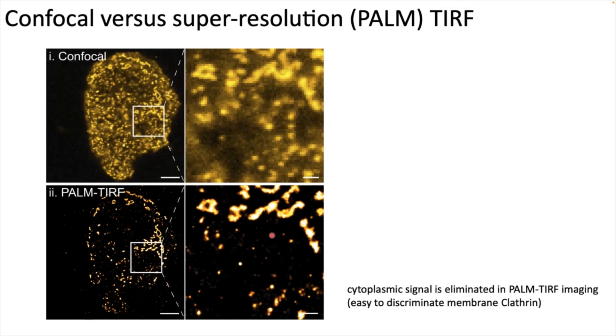It's just related to the fact that we are measuring in TIRF. And as a consequence, we only really image the clathrin that is on the plasma membrane. And on confocal, even though you have some Z sectioning, you still have around 600 nanometers that you image. And as a consequence, you get some of the clathrin that is just above the membrane being endocytosed. So some of these vesicles that show up on the confocal image, they are not present on the super resolution imaging.